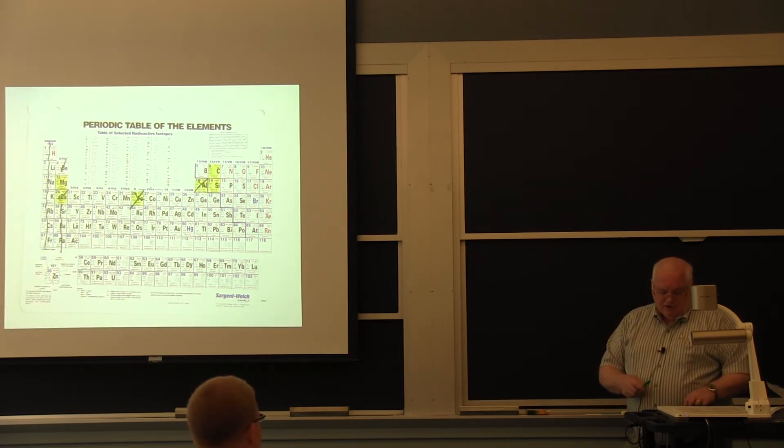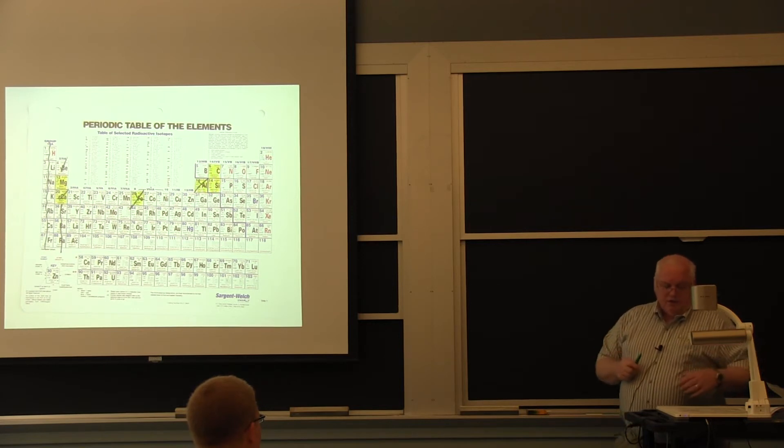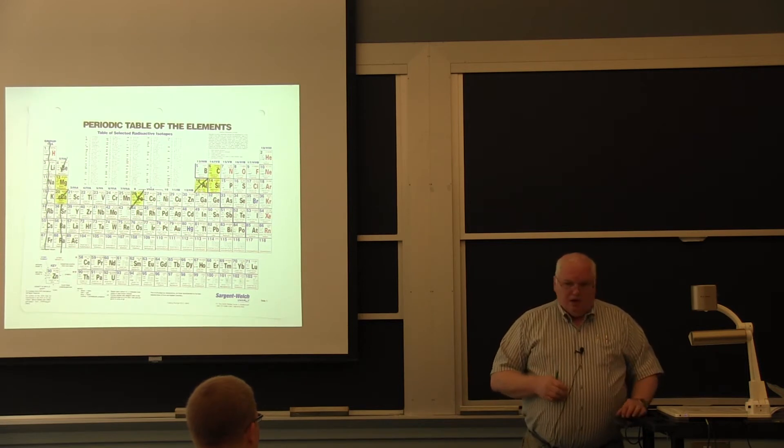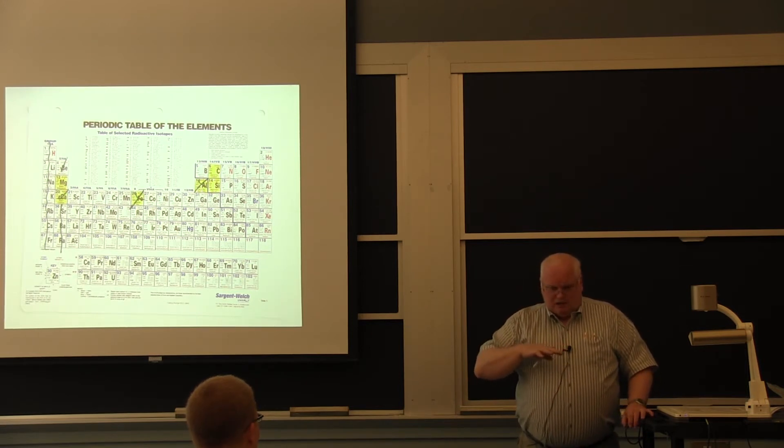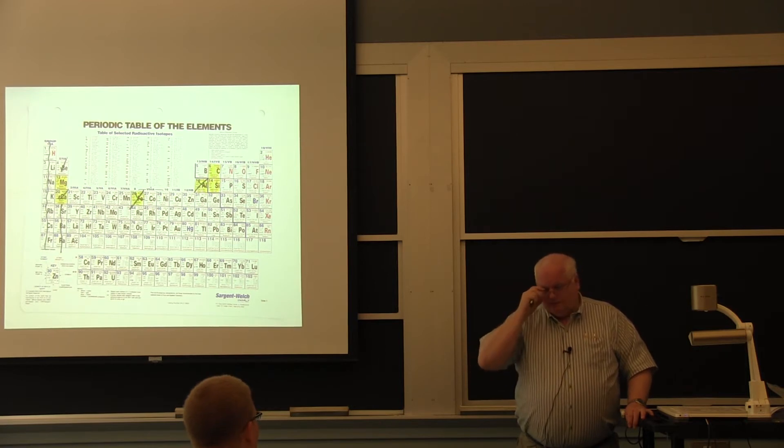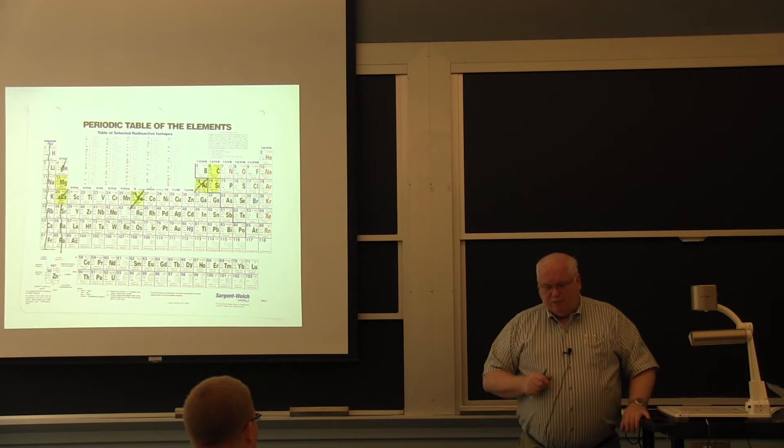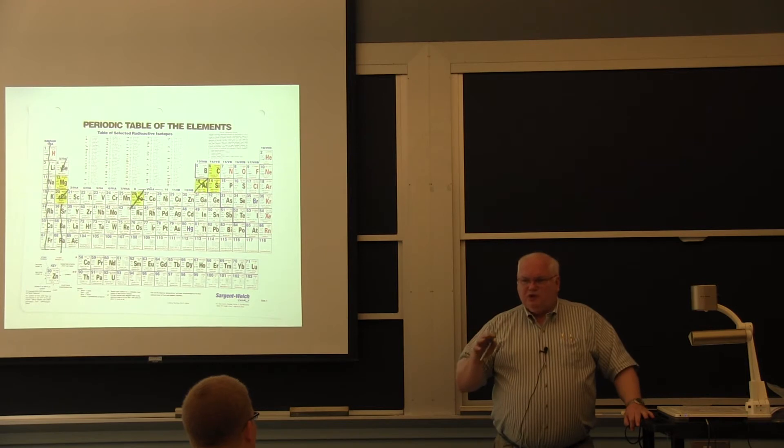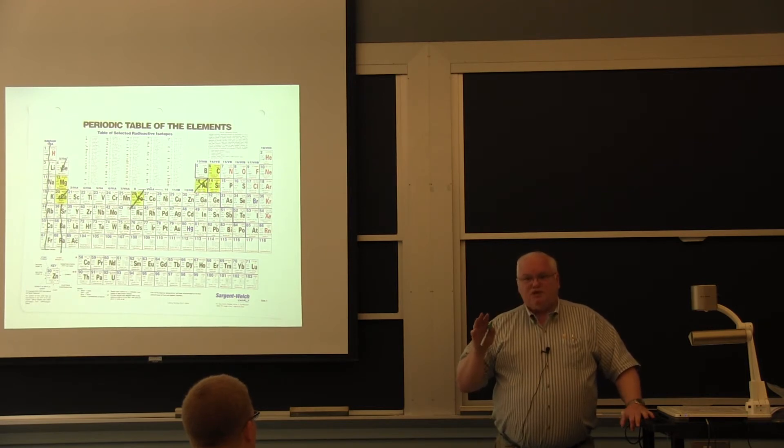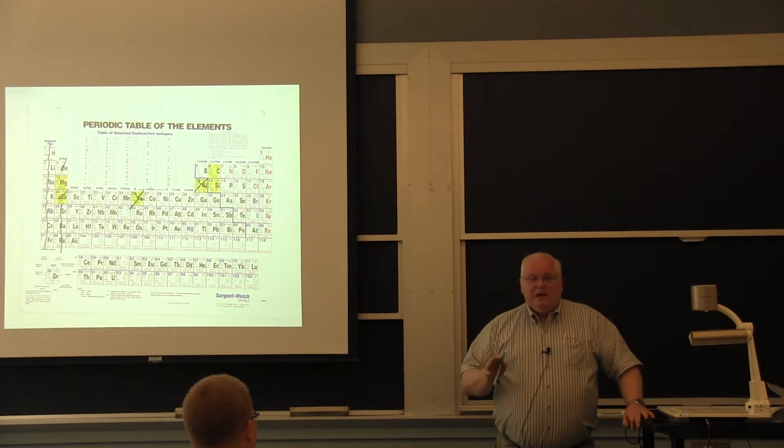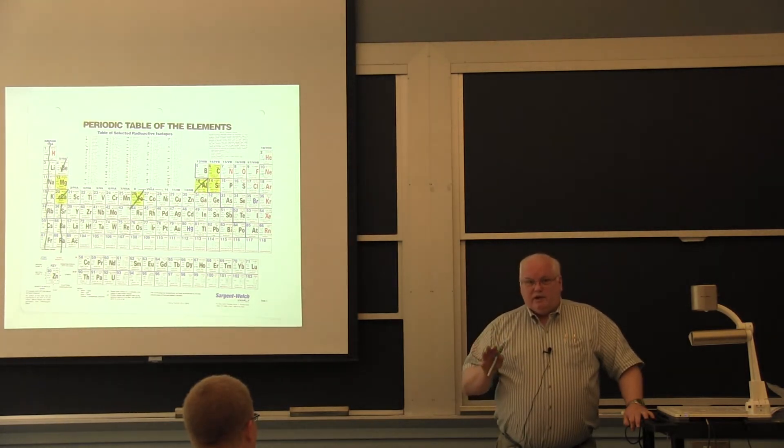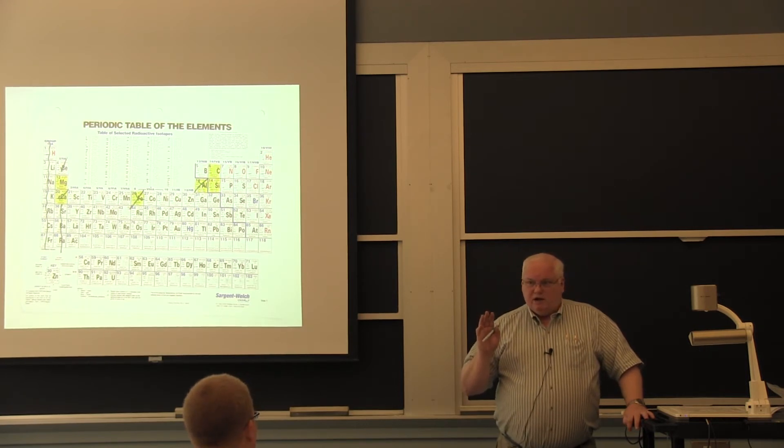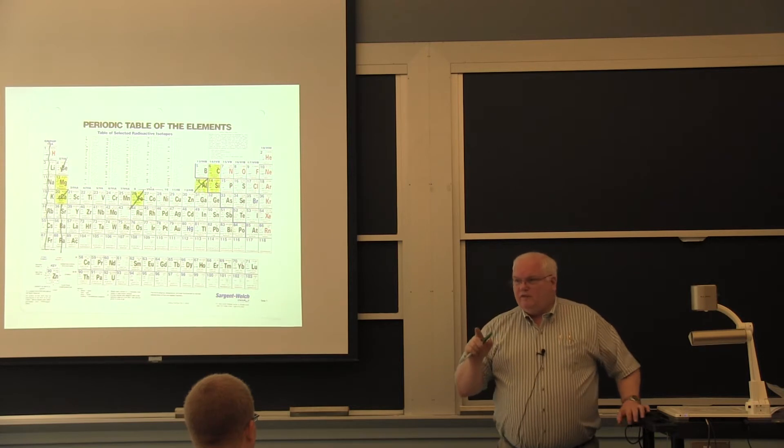Magnesium, a large fraction of the magnesium goes into anodes. Only a relatively small fraction, like 25%, goes into structural materials, castings usually, because one of the problems with magnesium, aside from the fact it's hexagonal closed-packed and you can't roll it very easily because it doesn't have enough deformation systems. And you try to deform it to get a general shape change, and because of the lack of slip systems - you learn about dislocations and things, well, they only work in certain materials like cubic metals. And magnesium is not a cubic metal. It's hexagonal closed-packed. It deforms by twinning and you will crack it if you try to give it a general shape change.